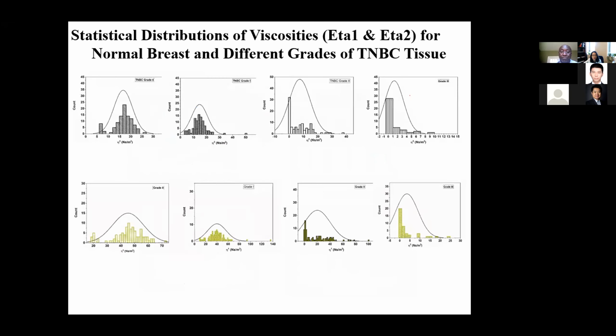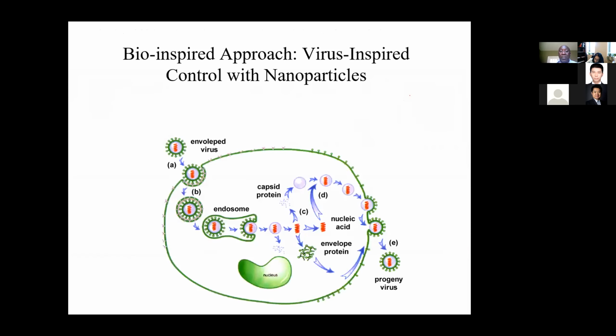And so when you look at the statistical distributions of the viscosities, it's interesting to see what you find. So for the normal breast tissue, you have essentially almost like a normal distribution of frequency count for the viscosity. As you go from grade 1 to grade 2 to grade 3, the distributions become skewed with the low viscosity tissue dominating the results. And so what you find then is that initially you have a statistical distribution that's almost normal, but as the tissues become softer, the viscosity and also the moduli reduce to very low values, and the nature of the distribution changes.